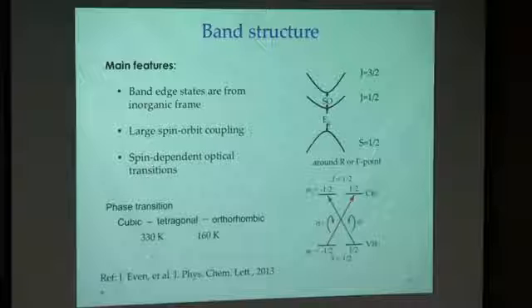I would also like to mention that the material experiences phase transitions as temperature cools down. The symmetry gets lower from cubic to tetragonal to orthorhombic phase, and we work with this low temperature phase. The symmetry of the bands is still approximately like that, with slight changes.